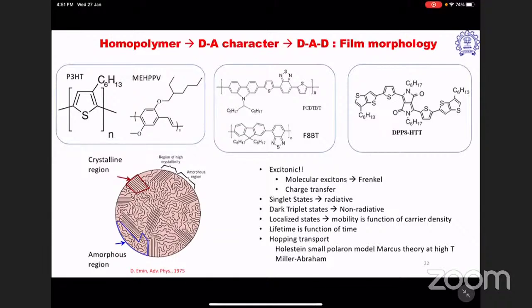Further charge transfer states can be generated if this material is put in contact with another type, in heterostructures. The exciton itself will have all kinds of nature depending on the spin, whether it's going to be a singlet state or triplet state. These are the things which suggest that it's not just that you inject charge carriers and get light output in an LED, or you shine light and get electron-hole pair generation the way things happen in silicon, where you shine light and generate free charge carriers. In organic solar cells, it goes through an excitonic route because of the low density.